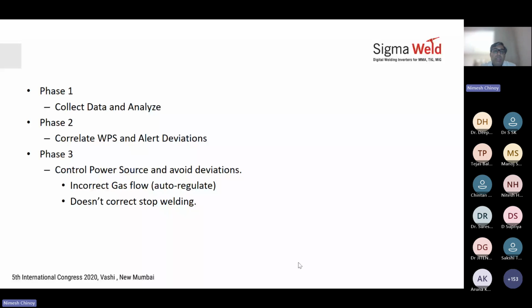Second is you correlate this analyzed data with the WPS, the welding procedure, and you can give alerts on deviations. That means you are not supposed to weld above 150 or below 100. If you did go beyond this range, the system should raise an alarm and say this was wrong. It was done at so and so time by so and so person. Please check.